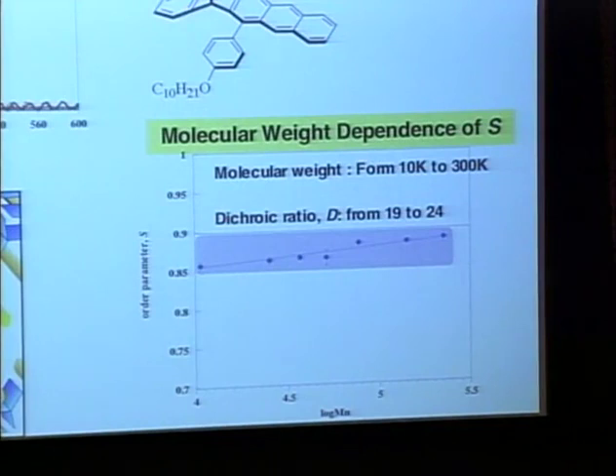And these molecular weights here, we have molecules that are microns long. A micron long molecule that is completely stretched out and it's in solution. And so now we're looking at ways you can gel liquid crystals, create these little micro trusses that go through a liquid crystal media to actually stabilize a device. And one of the things I say, the liquid crystal devices are rapidly evolving, not a static technology. And it's been driven by all these other competing plasma displays and OLEDs and PLEDs. And so they're not going to go away. And there's still a lot of room for improvement, particularly with aligning molecules like this.